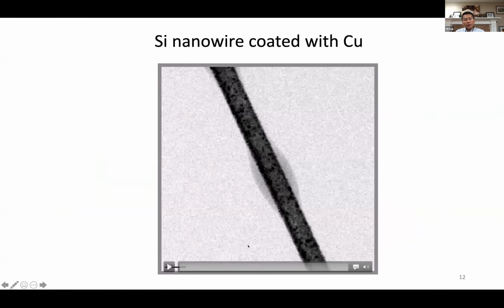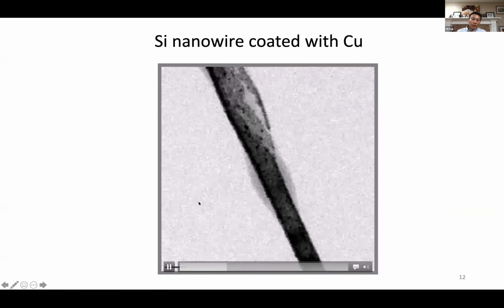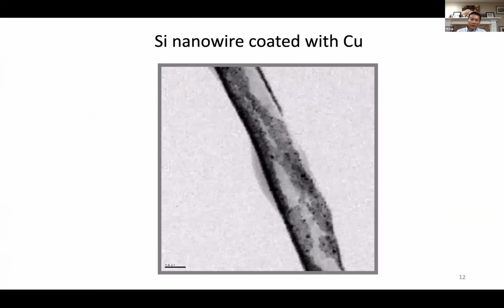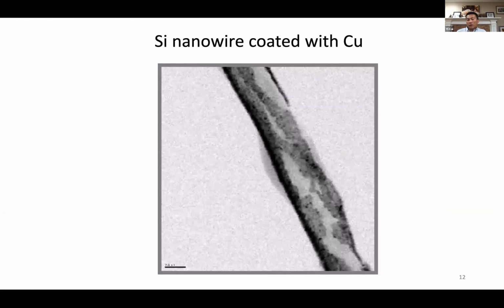For example, this is a silicon nanowire, 200 nanometer scale bar right here. We start to insert lithium, and we speed this up by about 5x. You see the volume expansion of silicon taking place, and there's a coating of copper, that's the black color, on the surface. And the lithiation taking place, this expansion is so powerful that it cracks the copper coating.